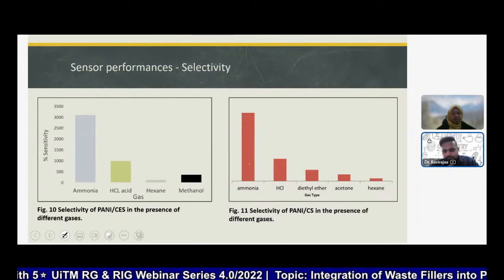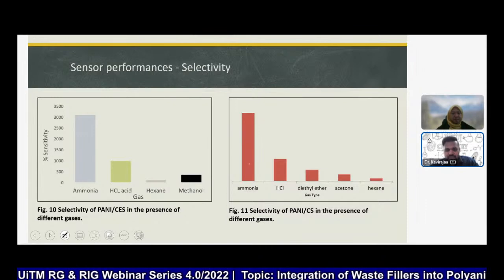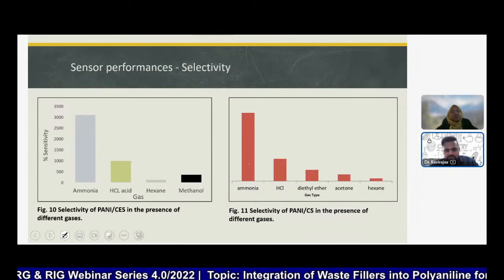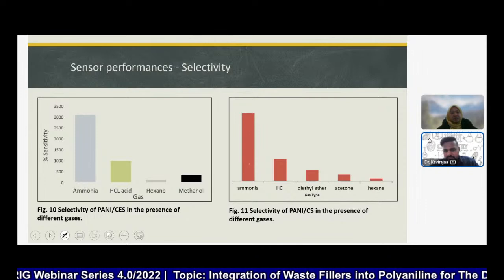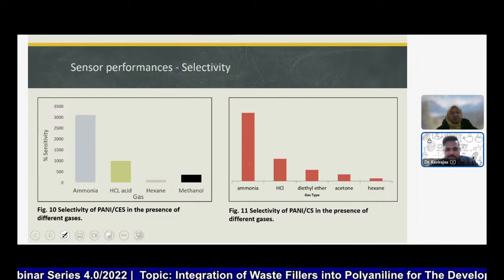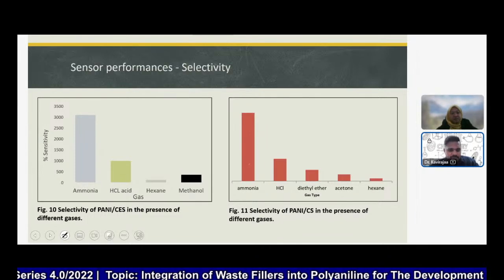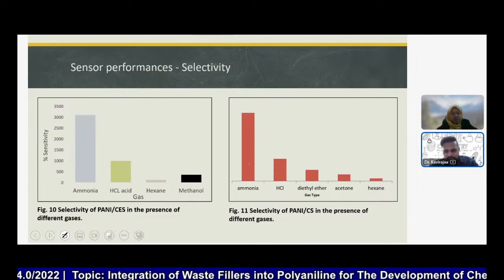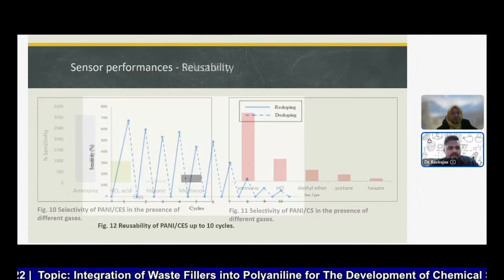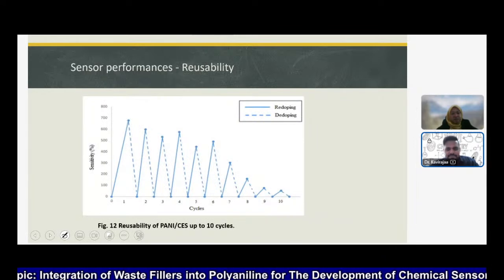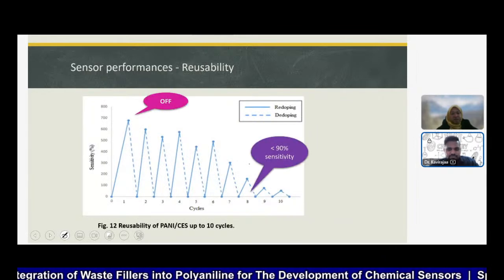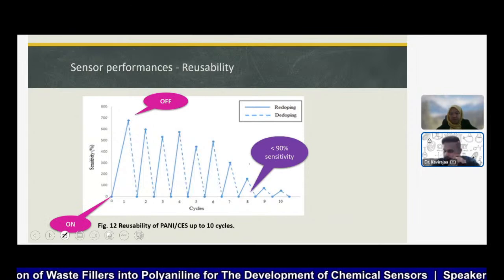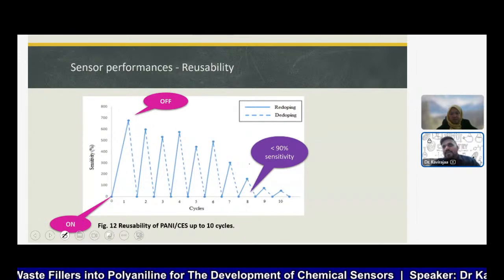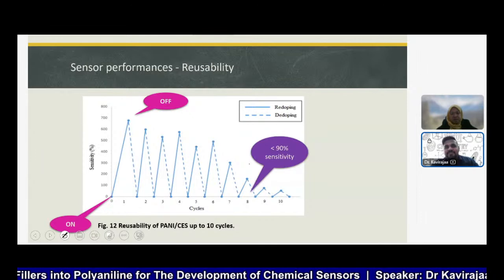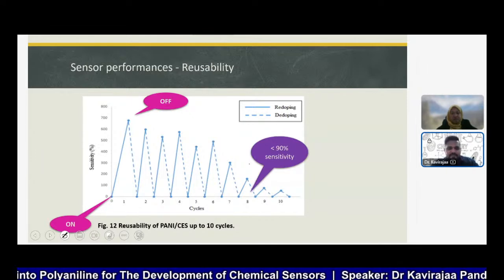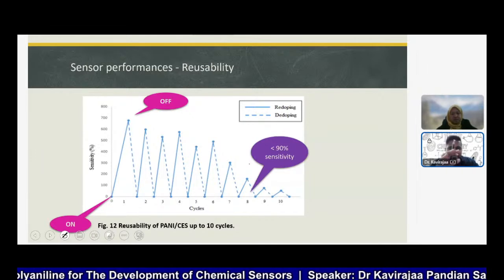In terms of other sensor performances, we cross-check with common gases. So we found almost all the time we will get a good selectivity towards ammonia, probably because of the dipole-dipole attraction of the electrons between the polyaniline and also the ammonia. And reusability wise, okay, so here, this is the way where we look into the gas sensor response and also the recovery time, but we could not report it over here. That's the thing, that's a problem actually.